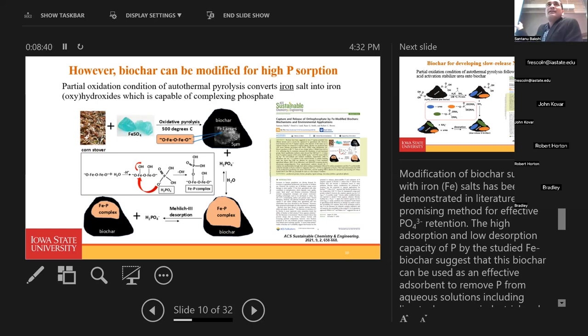Dr. Laird is also here, Robert Brown and me. So we published this paper in 2021. Modification of biochar surface with iron salts has been demonstrated in the literature as a promising adsorbent for phosphate. In this study, we have shown that biochar can be used as an effective adsorbent from aqueous solutions, including livestock manure, municipal wastewater, and agricultural effluents, and can be utilized as a slow-release phosphorus fertilizer. In addition, iron treatment or iron modification keeps the biochar surface pH in the acidic range, which is very necessary to reduce ammonia volatilization.